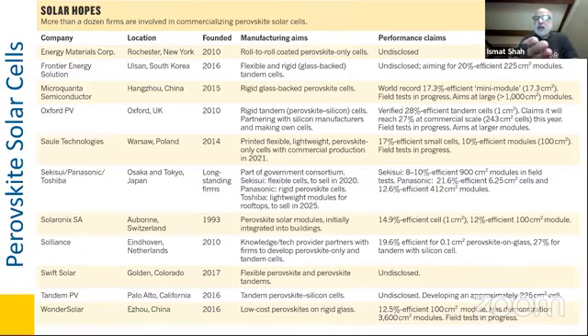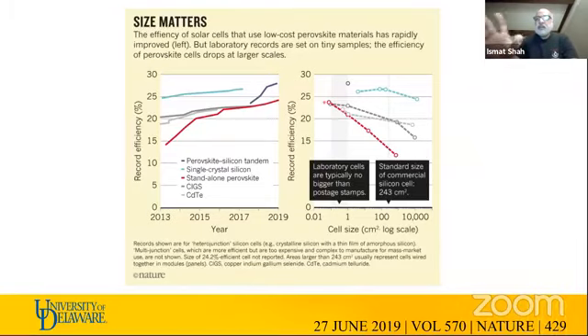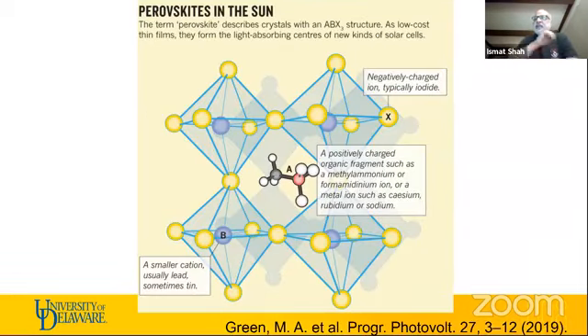But there are issues related to, most importantly, their stability. Size is one of the big factors that you can see here. This is an article that recently came out in Nature. Size is a very big issue. As soon as you go to bigger size, in all of these cases, the efficiency starts to come down. But most importantly, it's a very unstable structure. There is a stability issue related to the way the perovskite cell behaves as a function of temperature, particularly.